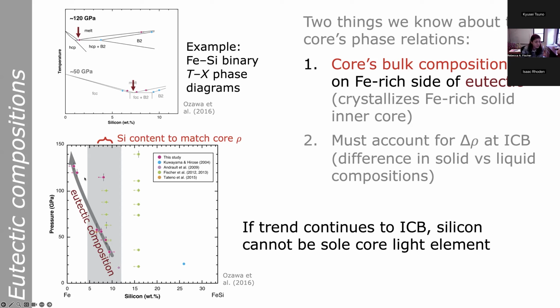And this curve down here comes from the same study, sort of combining constraints from a bunch of previous studies shown by these arrows on what the eutectic composition in the iron silicon system, how it changes with pressure, shown by this gray arrow. So at least over this pressure range, up to about 150 GPa, the eutectic composition is just shifting more and more toward pure iron. And in particular, it is on the iron-rich side of the kind of silicon content we would need to match the core's density if the core was just an iron silicon alloy, shown by this red symbol.